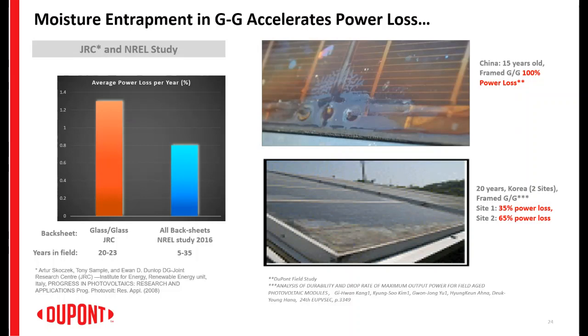The pictures on your right-hand side show delamination and corrosion issues in double glass modules, and as you can see, these issues are prominent at the module edges. This is what I was talking about in the last slide: the moisture goes inside through the edges, and that is why the issues of delamination and corrosion are more prominent along the edges of glass modules.